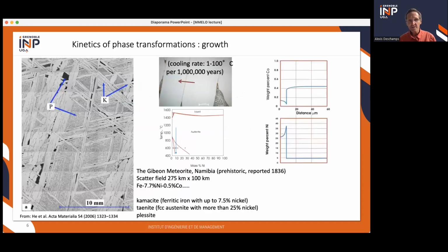The other example to show you that equilibrium can be far away is a study that was made in 2006 on meteorites. There were calculations showing that they were cooled down from the liquid state at about 1 to 100 degrees Celsius per 1 million years. So it's something where you would expect to be close to equilibrium. And actually during this cooling, it's basically a steel with nickel and cobalt, and you go through a two-phase, basically intercritical two-phase part of the phase diagram.